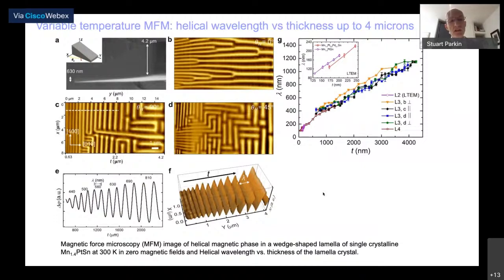And on the left, you can see a series of images in which, by applying in-plane magnetic fields, we can reorient these helical domains from one direction to another direction, to a direction in B, which is perpendicular to the lamella, and in C and D, which is along the length of this lamella. And we can see this beautiful sinusoidal variation of the out-of-plane component of the magnetization consistent with a helical structure. So it's amazing. The magnetic force microscopy and the Lorentz TEM agree with one another.